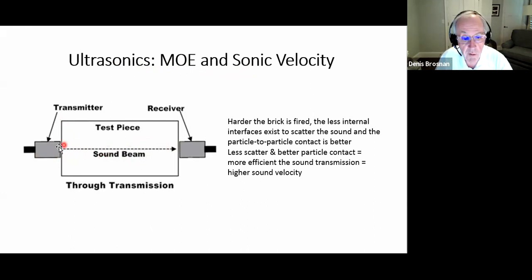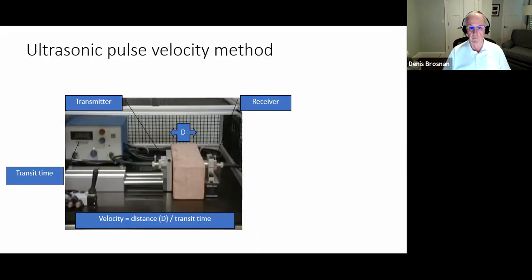The velocity of sound going from one place to another. There's a certain distance or thickness of the product, so it takes a little bit of time for the sound to go through, and electronically we can measure that time pretty easily. And the better particle-to-particle bonding that we have, meaning the more density, the faster the sound's going to go. So it's pretty simple. So ultrasonics are used a lot with products as they exit the kiln to determine their quality without having to send them to a laboratory. So it might be a quality control test.